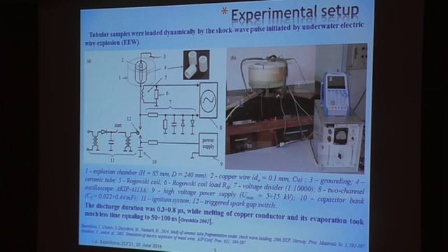Tubular specimens with an axial conductor were placed in a cylindrical chamber and the chamber was filled with distilled water. The shockwave was initiated by the electric explosion wire.